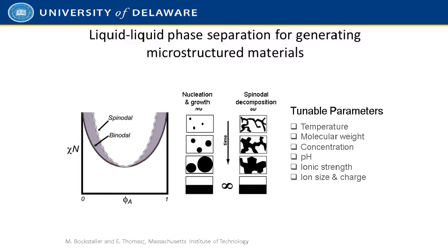One is indicated by the binodal curve, which is a nucleation and growth mechanism that results in the formation of small circular domains that mature and grow in size over time until, as you progress to the bottom layer, one observes a macro phase separated solution, much like you would see if you left an oil and water solution or emulsion sit over time.